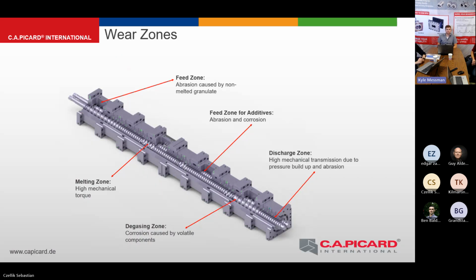I would like to start with the different wear zones we have in an extruder. We are starting with the feeding zone. In the feeding zone, we mainly see abrasion because we have non-melted granulates. Then it goes downstream to the melting zone, where we have very high torques and very high pressure in the extruder. What we mainly see at the kneading blocks is that they often have very heavy wear.